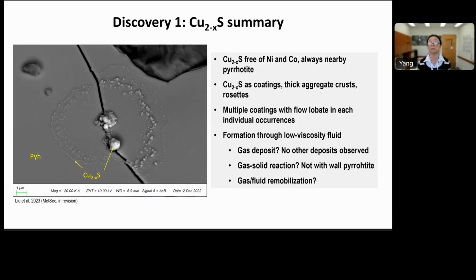So the take-home summary for the copper sulfide discovery is, copper sulfide is quite pure in terms of chemistry, with no nickel or cobalt associated with the copper sulfide grains. Nickel and cobalt are both chalcophile, sulfur-loving elements, so we don't really see that here. Copper sulfide occurs in different forms, but often together in each individual occurrence.